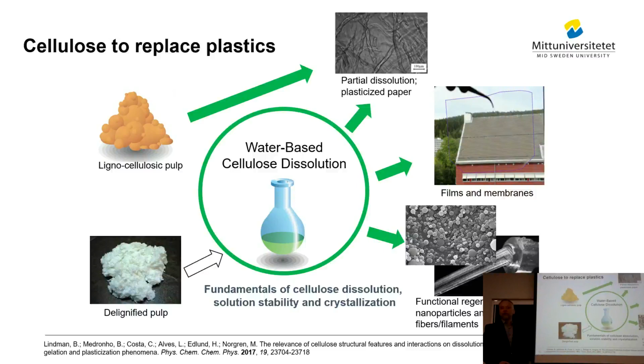If you look at polymers in general, there are hydrophobic interactions that are important for solubility. You might not see it immediately from the chemical structure, since it might be very, very small things that actually act in the direction of the hydrophobic interactions. But you will recognize it if you do research around it. So we started this work in 2015, looking at how to treat cellulose materials in different ways by using water-based solvents, and usually we use these urea hydroxide combinations since it's a simple system.